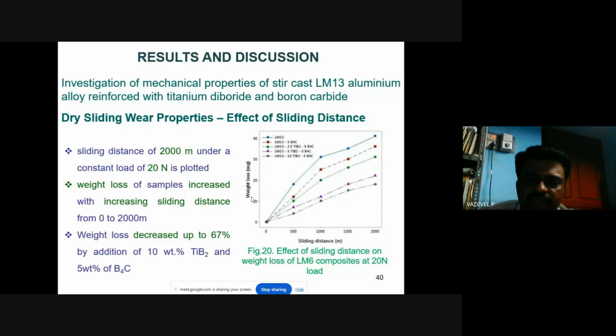The wear test is done with a sliding distance of 2000 meter under a constant load of 20 Newton. The graph shows the sliding distance on the x-axis and the weight loss in milligrams on the y-axis. A number of compositions were plotted with the distance of 2000 meter at a constant load of 20 Newton. The weight loss of these samples increased with the increasing sliding distance from 0 to 2000. The axis shows weight loss of 0, 10, 20, 30 and 40 milligrams.